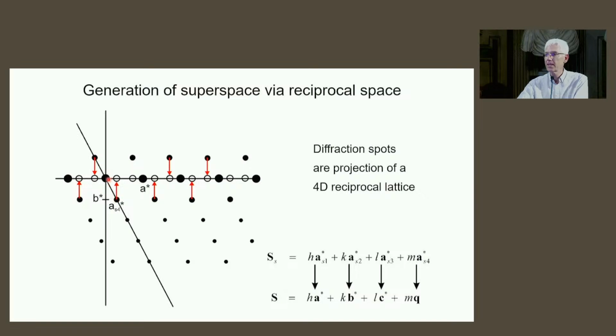Here it's A2 star, and it is Q in physical space, and B star or A S4 star in the additional dimension. And you see nicely that the satellite reflections are considered as projections from reciprocal lattice points in 4-dimensional space, whereas the line m equal 1 projects on Q, and the line m equal minus 1 projects on minus Q. And that's the reciprocal unit cell in superspace.